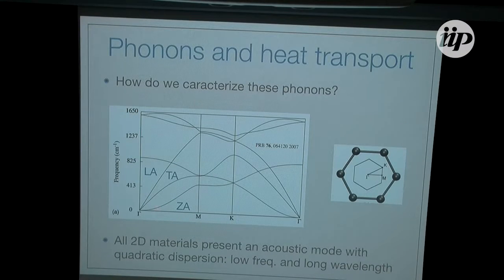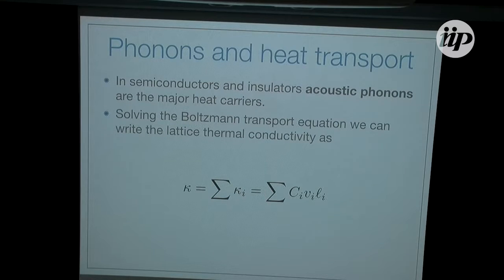So how do we characterize these phonons? We have here the dispersion relations for them. So essentially you have a frequency as a function of the wave vector of the phonons. And we are particularly interested in these 3 acoustic modes, which are the modes that have frequency 0 at the gamma point, which is at the center of the Brillouin zone, right? In graphene, you have two linear modes, the longitudinal and the transverse mode, and then you have a flexural mode, which are vibrations of the atoms out of the graphene plane, like a membrane. And these are very special because they have this quadratic dispersion. All the unusual heat transport properties of graphene come exactly from these flexural modes. This is clear now, but it wasn't the case a few years ago.